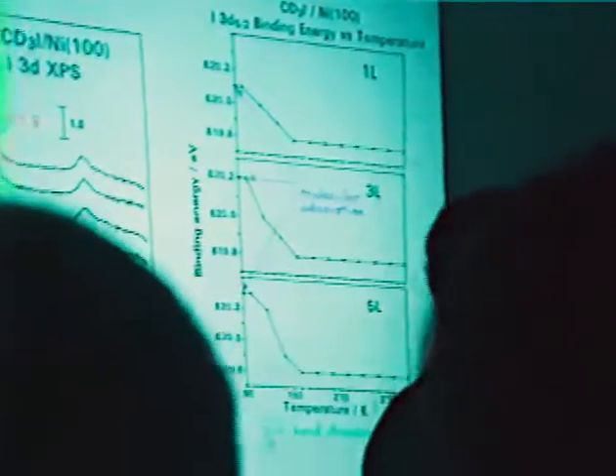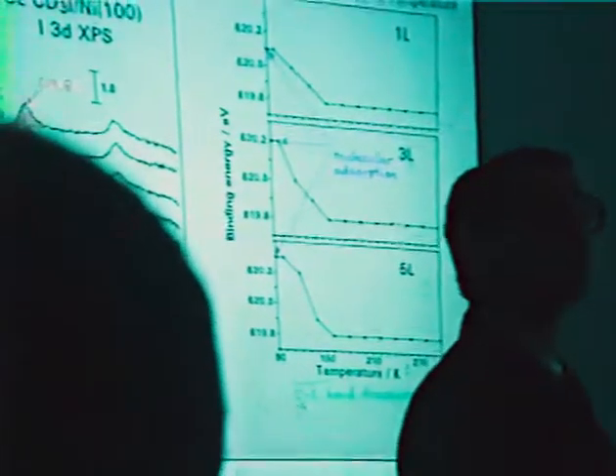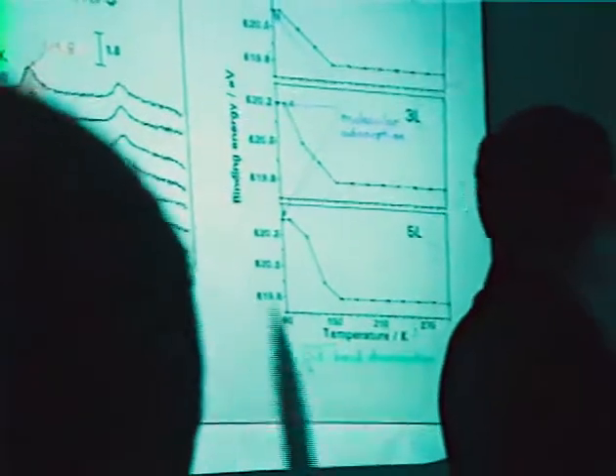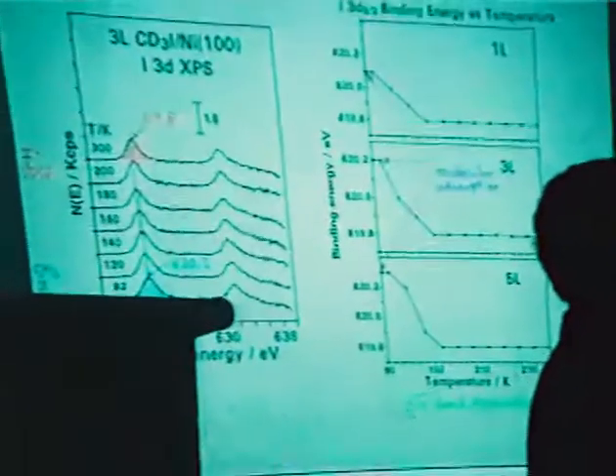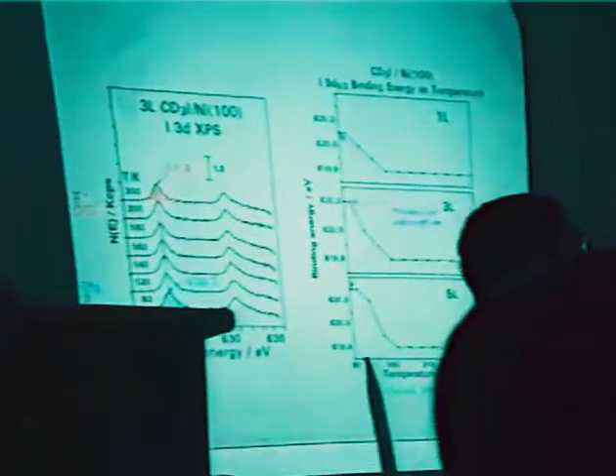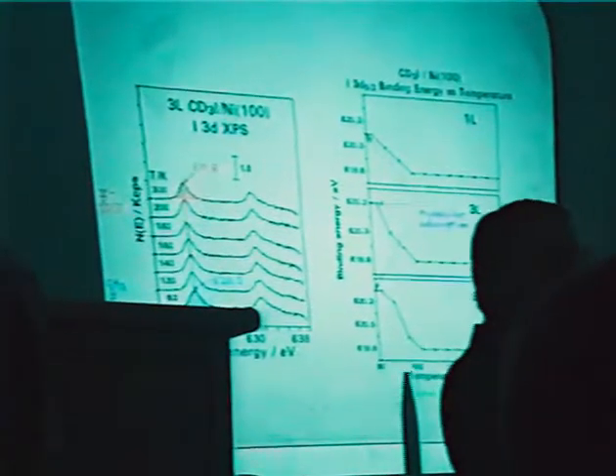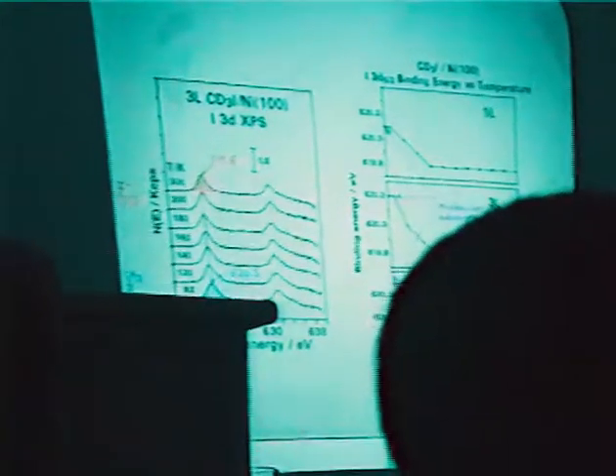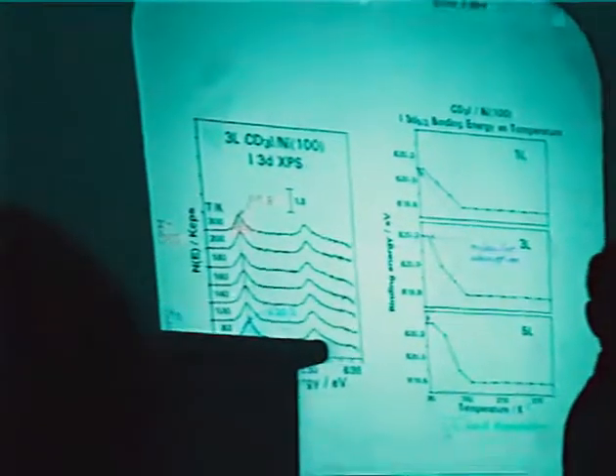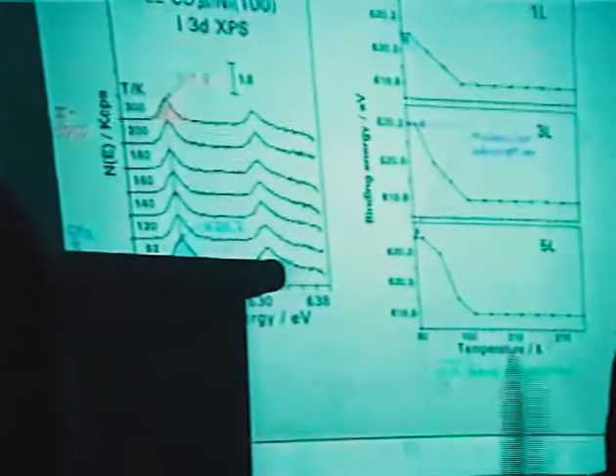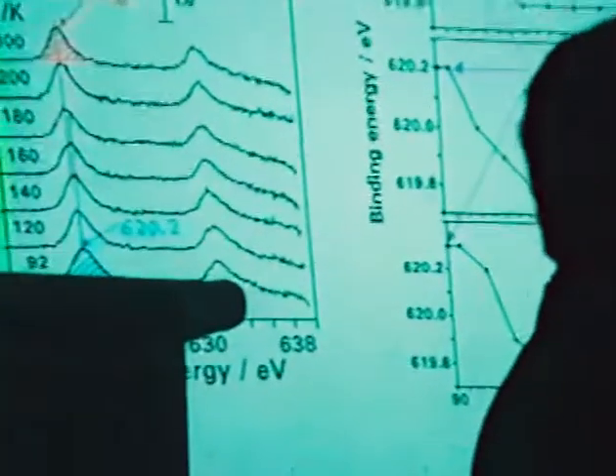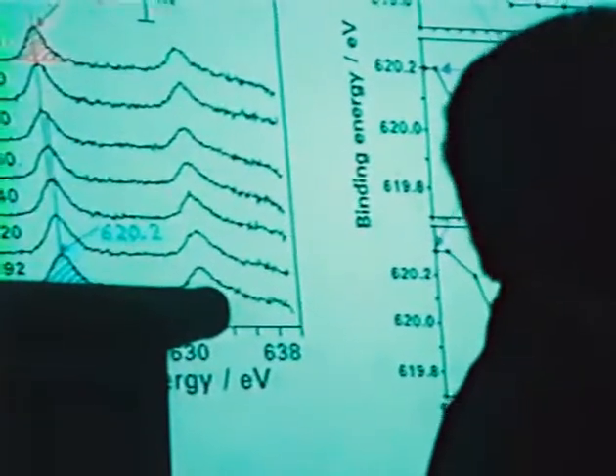It works on nickel as well. So when you start at low temperatures, around 92 degrees Kelvin or so, as low as we can put this methyl iodide on the surface, we get an iodine peak at a position that is characteristic of just molecular methyl iodide. But as you heat up the surface, you see a shift of about 0.4 eV into that peak. And we identify that shift with the breaking of the carbon-iodine bond because this binding energy corresponds to atomic iodine on the surface. We see that the reaction takes place somewhere between, if we follow the position of the peak versus temperature, you see it's a wide range of temperatures in which that peak shifts. It starts at about 120 Kelvin or so, and it's over by about 160 Kelvin.